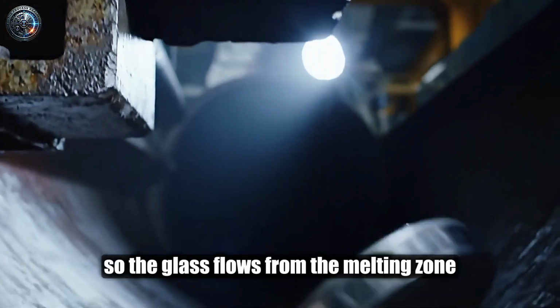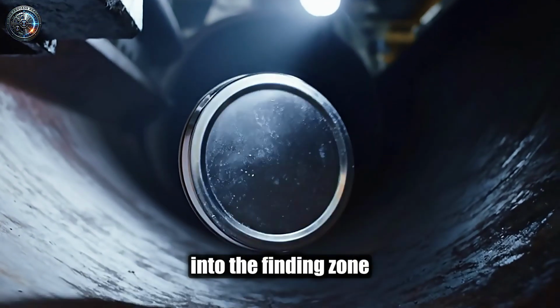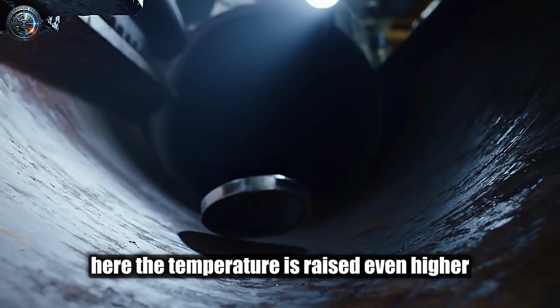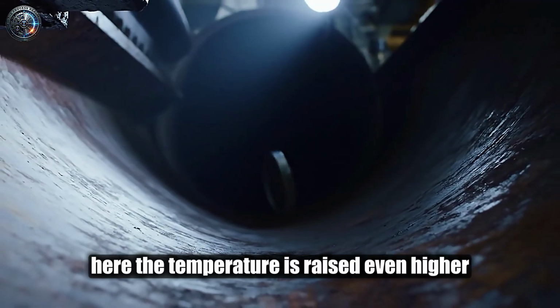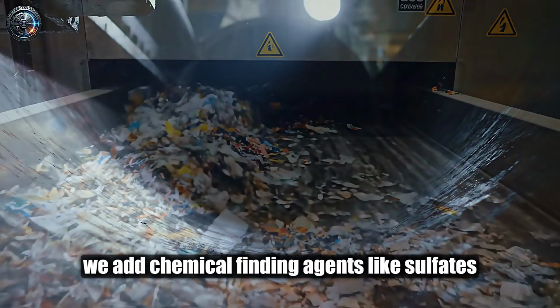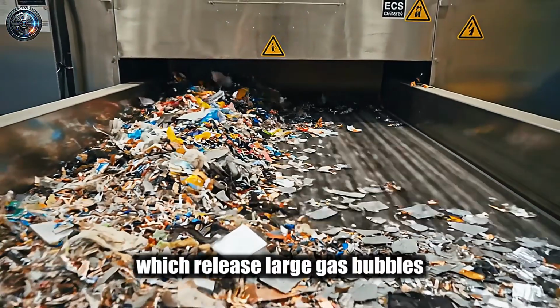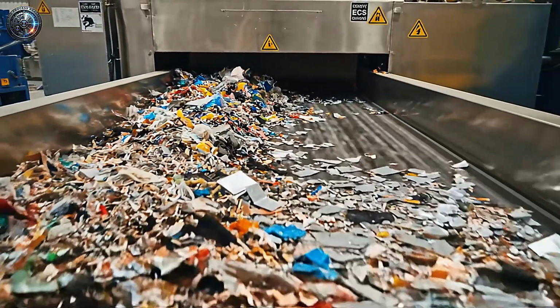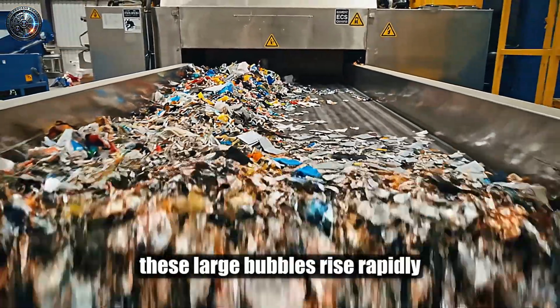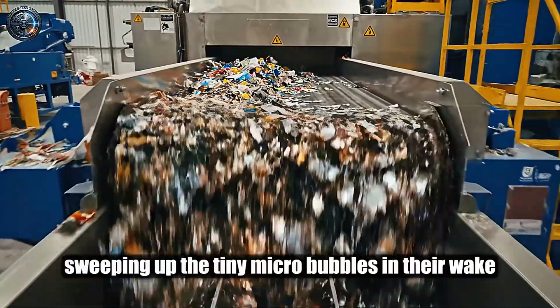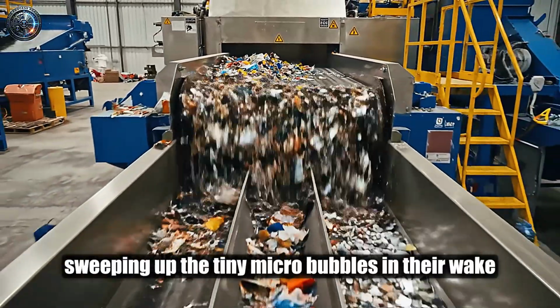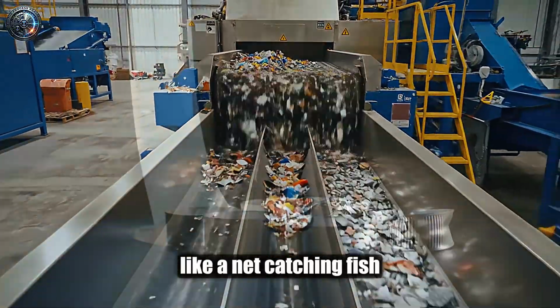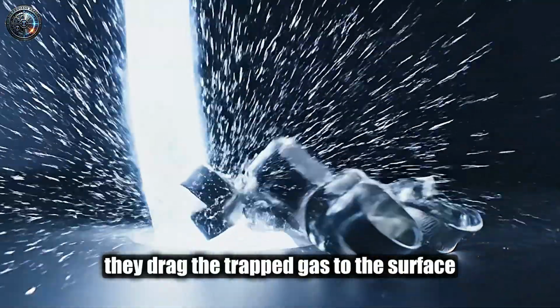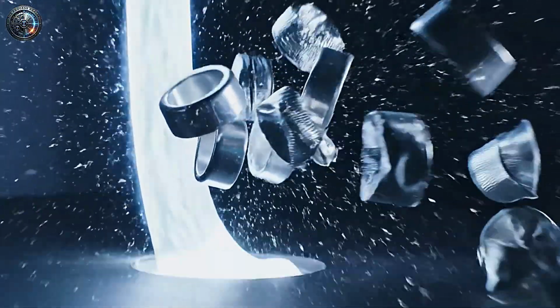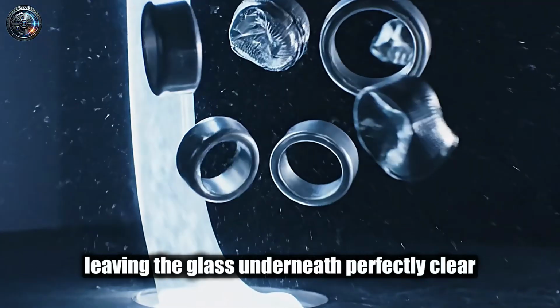So the glass flows from the melting zone into the fining zone. Here, the temperature is raised even higher. We add chemical fining agents like sulfates, which release large gas bubbles. These large bubbles rise rapidly through the molten glass, sweeping up the tiny micro bubbles along the way, like a net catching fish. They drag the trapped gas to the surface, leaving the glass underneath perfectly clear.